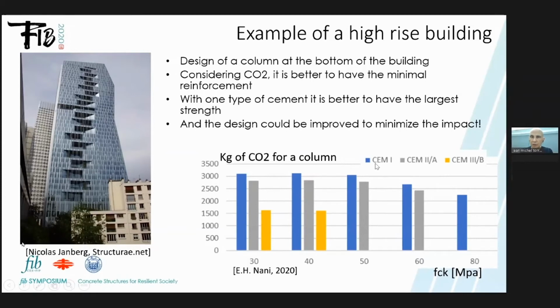For instance, if the concrete uses the same one cement, you could see that when you increase the strength, you have a lower amount of CO2 for a given column. And it's the same with the CEM II. Of course, with CEM III, considering slag with no impact, you have a lower value. And we are not able to obtain very easily high strength concrete with slag. Of course, I know it's possible, but it was not considered here in the study.